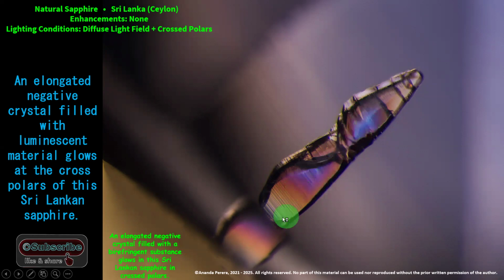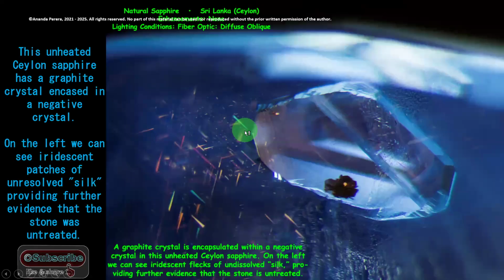You can see the luminescent material inside the negative crystal, so it glows under the crossed polars of this Sri Lankan sapphire. You can see the luminous material glowing under the crossed polars and diffuse light field. It shows the stone is not heated, no enhancement. It is natural sapphire.